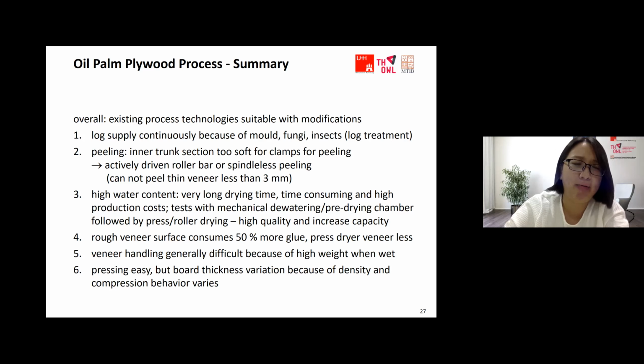We can now peel deep veneer, up to 6 millimeter or maybe more, but not very thin as is now. So basically, the crucial part is the drying process. A lot of work has been done by researchers in Malaysia to shorten the drying time, increase the quality of the veneer, and increase the capacity of the mill. The rough veneer surface is also a main issue during the gluing process because it consumes more glue,